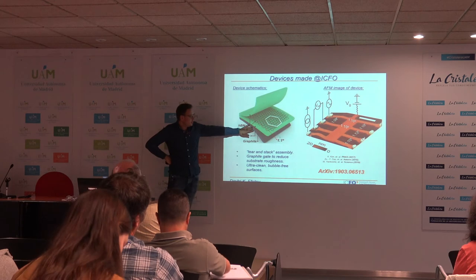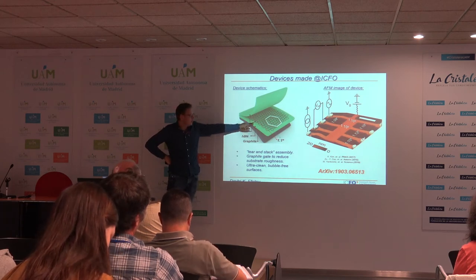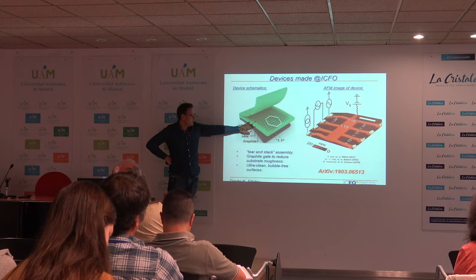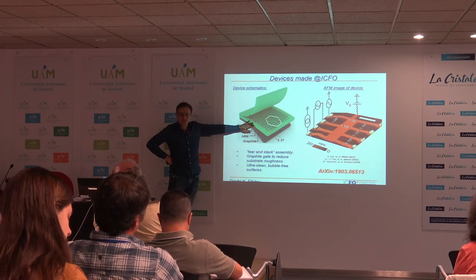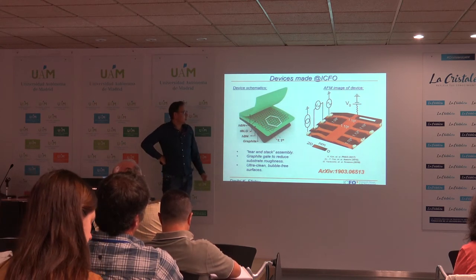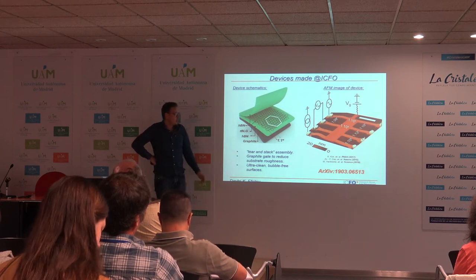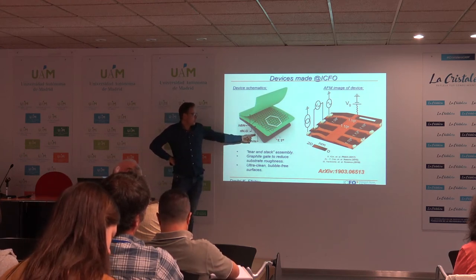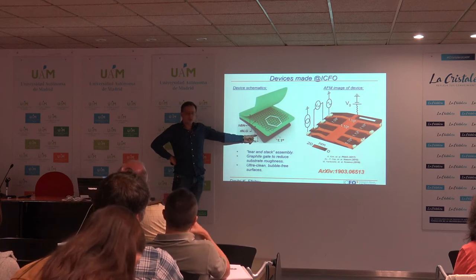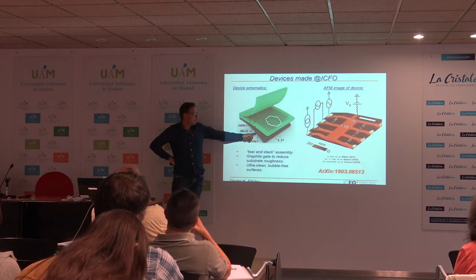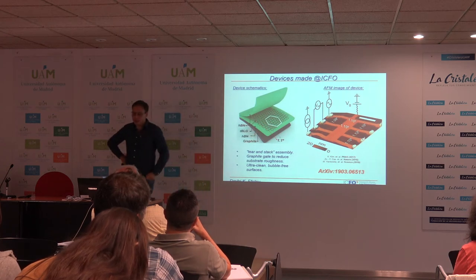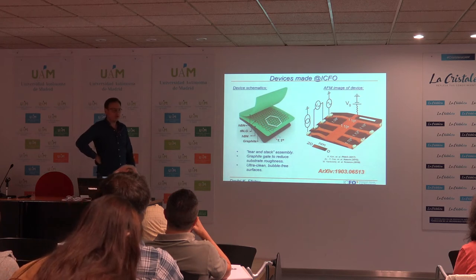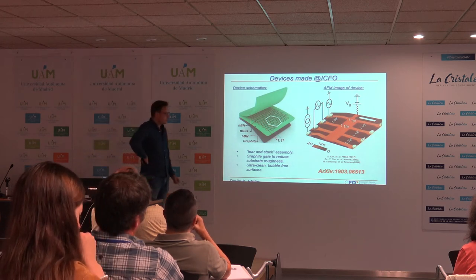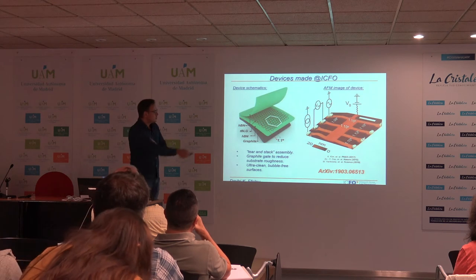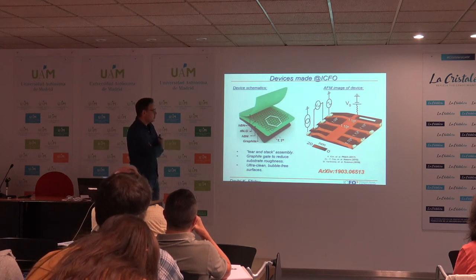So the devices we're making are, again, as follows. We use a graphite backgate, which is separated from the twisted bilayer graphene by a very thin hexagonal boron nitride dielectric. And then we cap it off with another layer of HBN. And as was explained in the previous lecture, we can just apply a voltage to this graphite and capacitively couple it to the graphene. So we can use this graphite just as a local gate, and we can tune the carrier density through the graphite. Okay, and so this is an AFM image of a typical device which we're having.